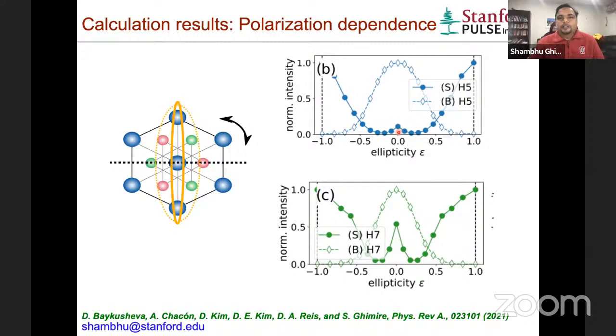The response is completely opposite. It actually grows, the intensity grows as a function of the ellipticity. And in this case, for the fifth harmonic, it becomes maximum for circular polarization. There is a similar trend for all harmonics, slightly different on where exactly they pick up the maxima. But there is a general trend that the emission from the surface states is much more efficient for elliptically polarized fields.